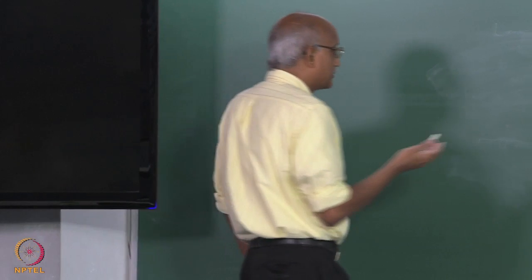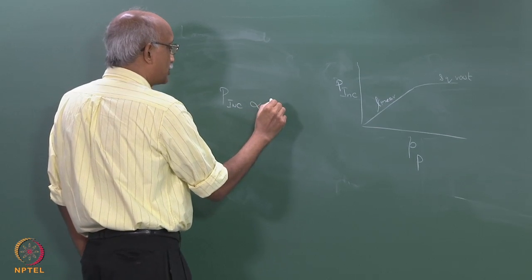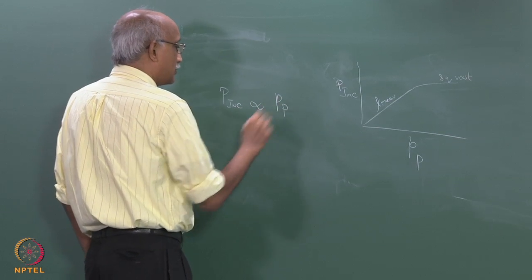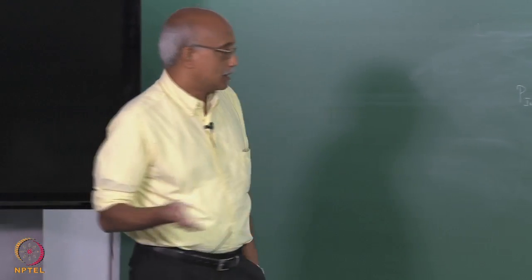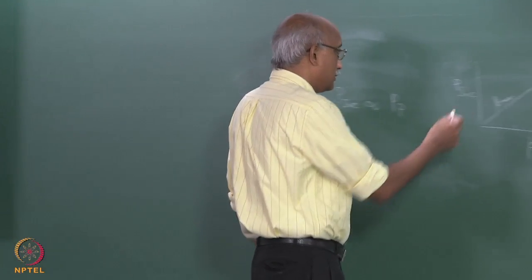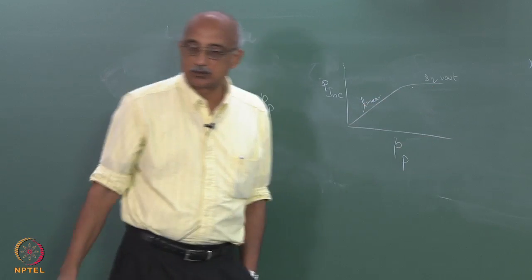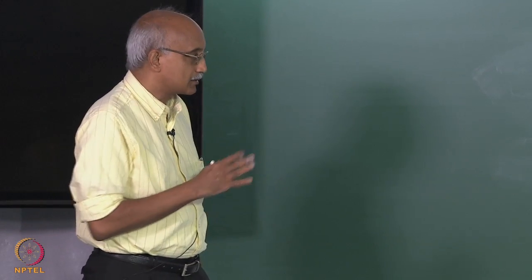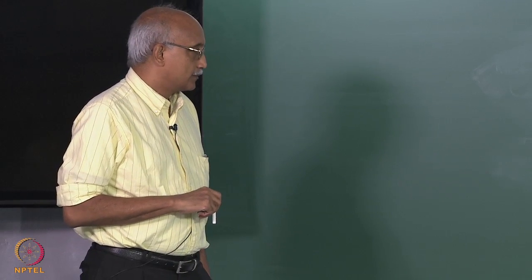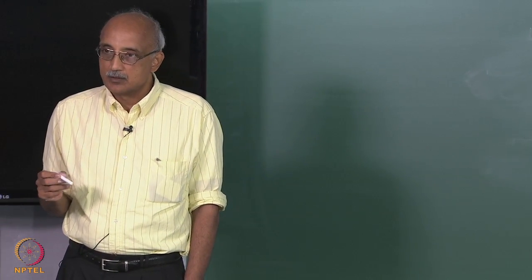The reason being that the P incorporated is obviously proportional to the partial pressure of phosphorus that is in contact with the substrate. And unless it saturates, you wouldn't expect this type of behavior. And by the way, this is not related to saturation. There are plenty of available sites in your silicon to accommodate more phosphorus molecules. So, it is not due to saturation. The reason that this happens is that the thermodynamics of the system changes as you change partial pressure.